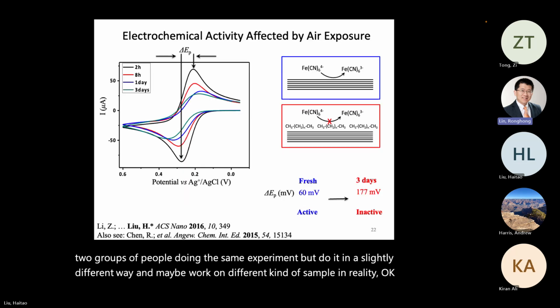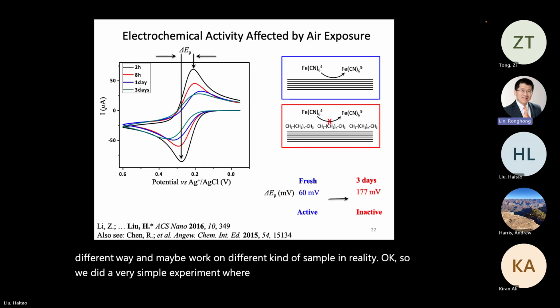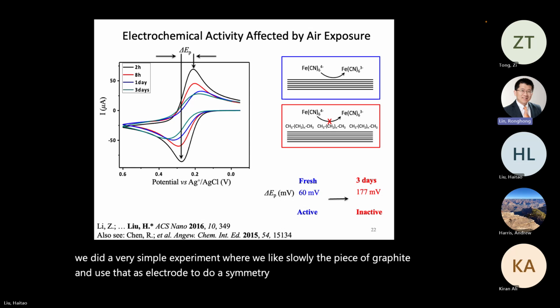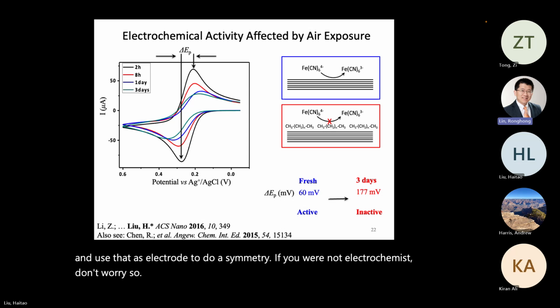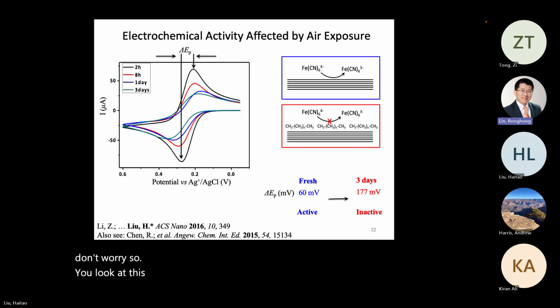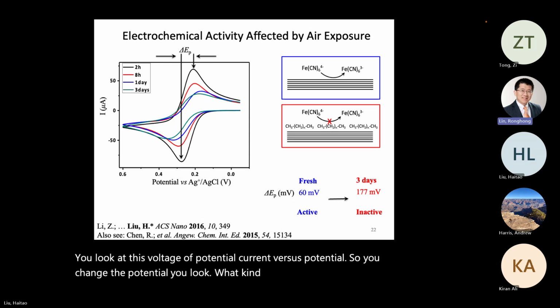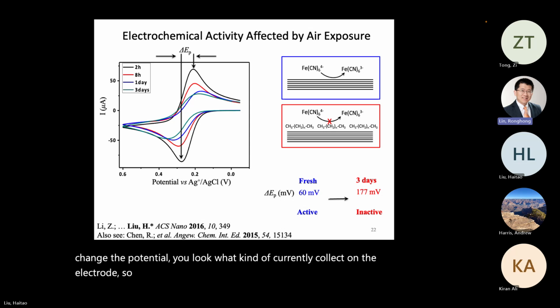So we did a very simple experiment where we exfoliate a piece of graphite and use that as an electrode to do a voltammetry. If you're not an electrochemist, don't worry. You look at current versus potential. You change the potential, and you look at what kind of current you collect on the electrode. The higher is usually better. That means your electron transfer is faster.